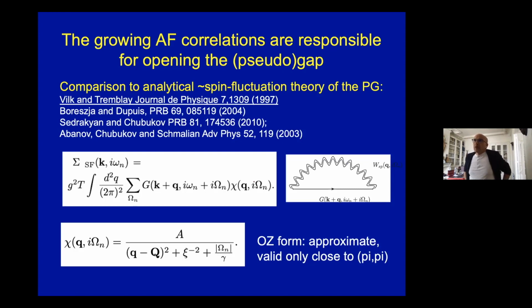So obviously, the growing of this antiferromagnetic correlation is responsible for opening the insulating pseudogap in that case. So this is a long wavelength phenomenon. And there is a beautiful theory of this that was put forward many years ago by Vilk and Tremblay, based in part on the so-called TPSC method, that basically amounts to analyzing the opening of the pseudogap through these spin fluctuation kind of diagrams, with semi-normalized couplings.